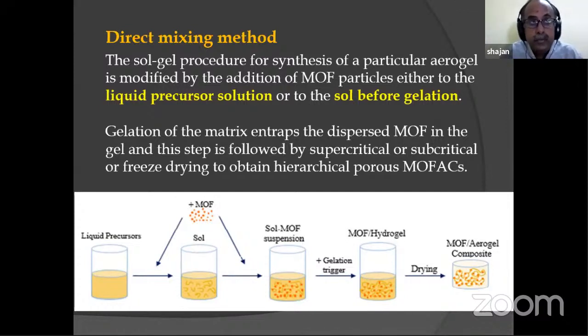So that is one case. How to avoid this? When we start adding the MOF, you have to constantly stir the liquid for, say, 6 hours, 7 hours. You have to stir the entire solution. Then you have to allow it for condensation. Otherwise, agglomeration will happen. This is point number one.